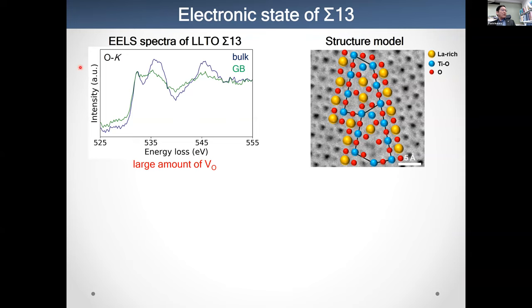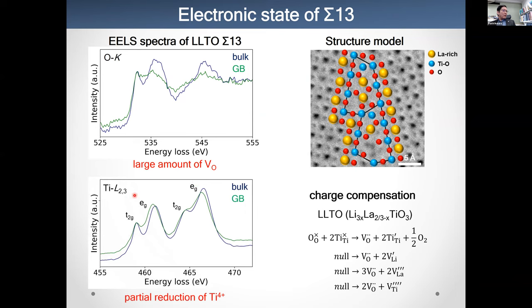Then we again investigate the yields of the oxygen K edge from the grain boundary and bulk. If we look at the grain boundary, this is broad compared to the grain bulk structure. That means that a large amount of oxygen vacancies must be introduced around the grain boundaries. We also measure titanium L2,3 edges, grain boundary and bulk, and a little bit of chemical shift occurs. This is very different from the case of the sigma 5 boundaries. This indicates that partial reduction of titanium 4+ occurs, which means titanium 3+ is included. And the structure is like that.